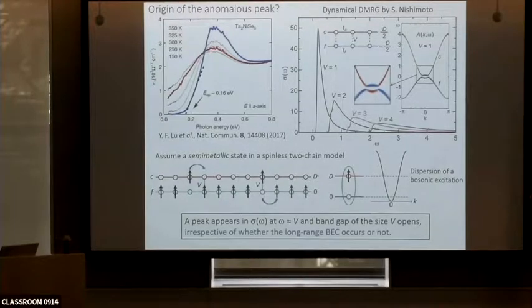No, but I perfectly understand this. What I'm trying to say is that the parameters you put in the model have to be consistent with the screening you have in the material in whatever correlated system. What you are putting in is an unscreened Coulomb interaction in an otherwise screened system, which is highly screened because it's either semi-metallic or metallic. Then there is a second thing: you decide to kill the screening. We do not include the screening effect.